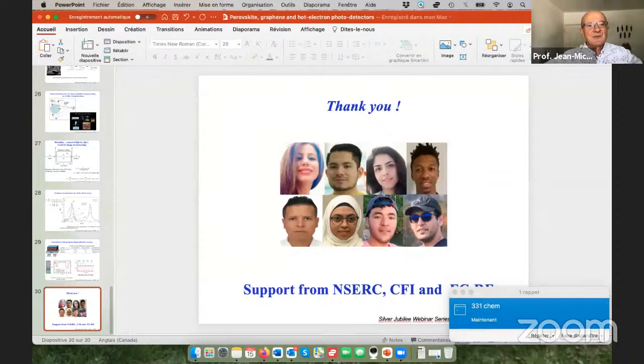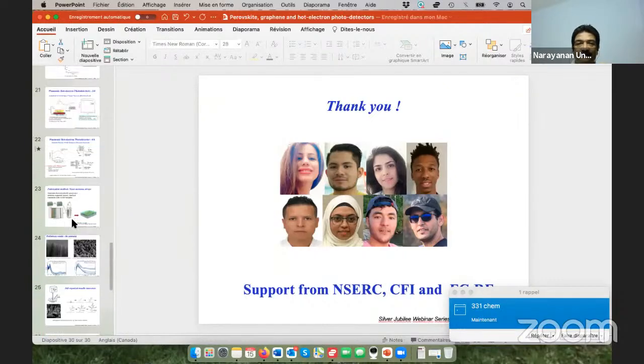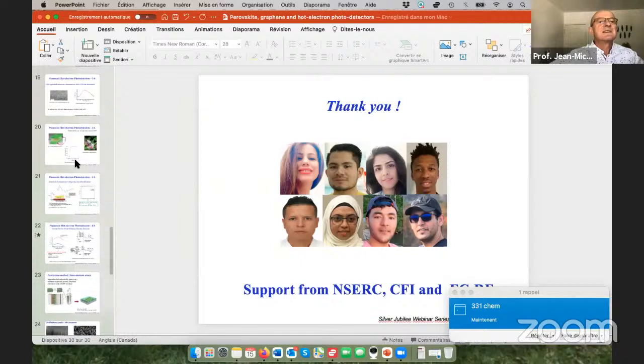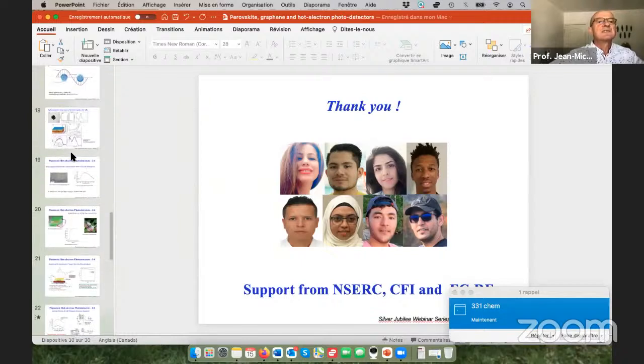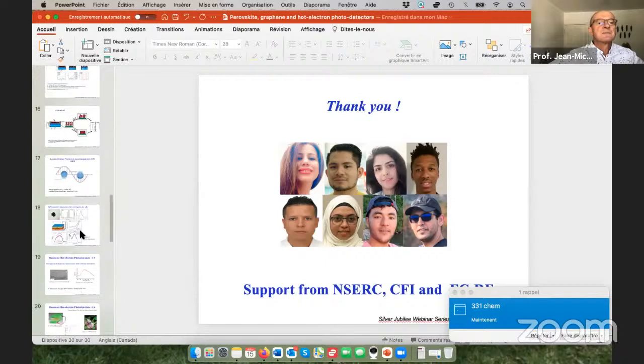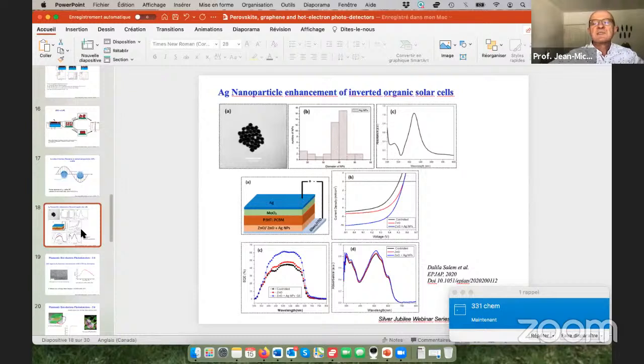It's because the thickness of our material is not huge, so the material still has some transparency. I can go back to the transparency, slide number 18. There's still some light crossing the device. So actually, when you measure the absorption, you measure what is transmitted. You see that at maximum it goes to 0.8, so that means there is 20% of transmission. What matters is how much transmission we are left with.